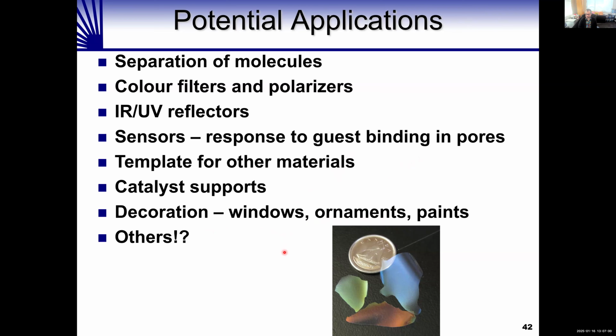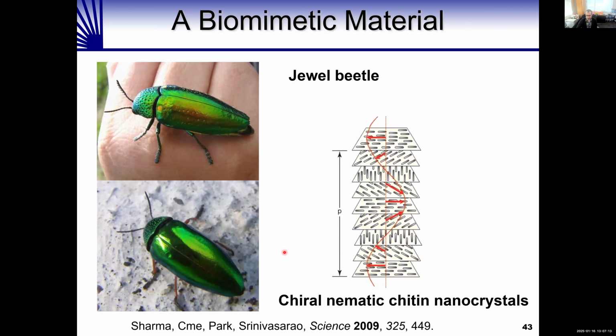Now, I started off talking about nature, and you're probably wondering what the connection with these materials is, beyond the fact that they're made using cellulose nanocrystals, a natural material. It turns out that this beetle, called the jewel beetle, native to many parts of Asia, has these beautiful iridescent exoskeletons. The iridescence comes from the fact that on the surface of this structure it has a chiral-nematic organization of chitin nanocrystals. So this beetle has evolved a way to make a left-handed chiral-nematic ordered structure of chitin nanocrystals on the surface to give it iridescence. Our materials are kind of a mimic of the jewel beetle.